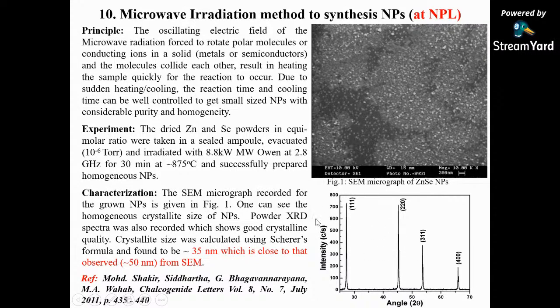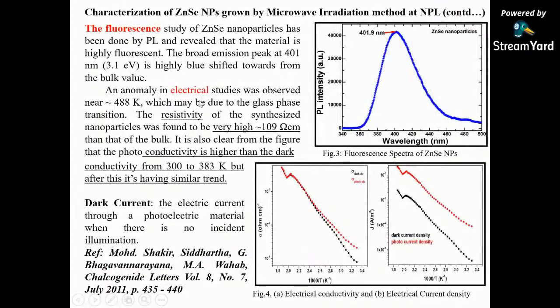Powder XRD is better to get the crystallite size, not the particle size. Sometimes the particle size may be higher. In the powder XRD, we got 35 nanometer, whereas with SEM we got a size of 50 nanometer. This is more reliable. So these are in the nano scale.